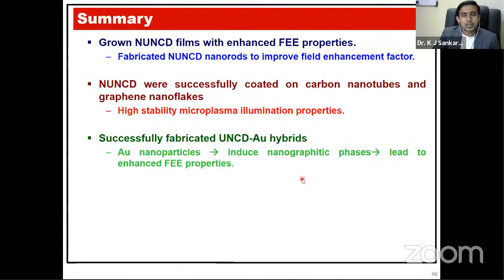So as a summary, we have achieved NUNCD films with enhanced field electron emission properties, and then we fabricated NUNCD nanorods with high field enhancement factor. And these NUNCD films can be coated on CNTs and graphene nanoflakes to achieve high stability microplasma illumination properties. We have also successfully fabricated the UNCD-gold nanohybrids, and these gold nanoparticles induce nanographitic phases, which leads to the enhanced field electron emission properties.